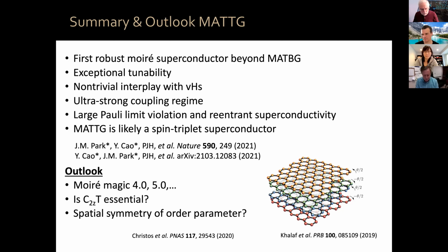Hi, thanks. A very interesting talk. Incredible data. One of the ways you can test for a spin triplet superconductor is looking at the spin susceptibility, for example, in an NMR measurement or a Knight shift measurement. Obviously, you don't have so many atoms in your sample, but have you thought about some way to probe the spin susceptibility? So indeed, we would love to be able to do a Knight shift measurement in the system, but as you